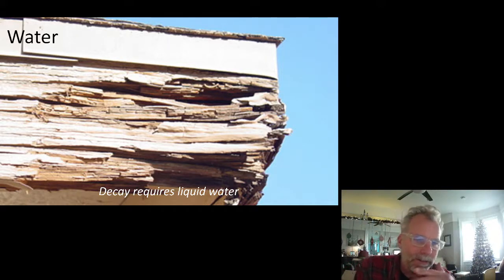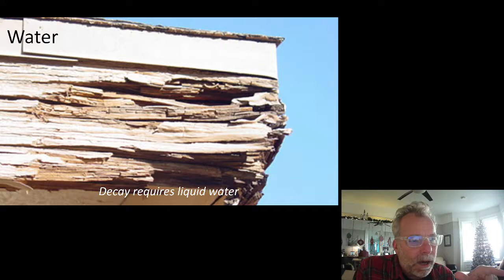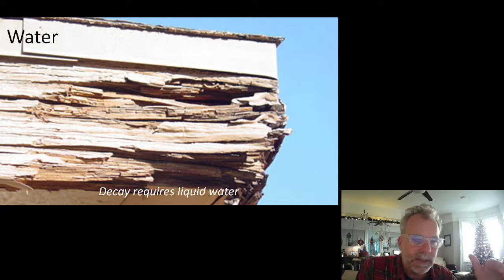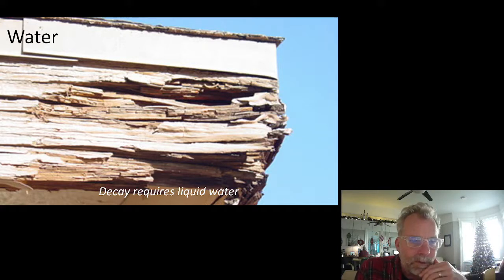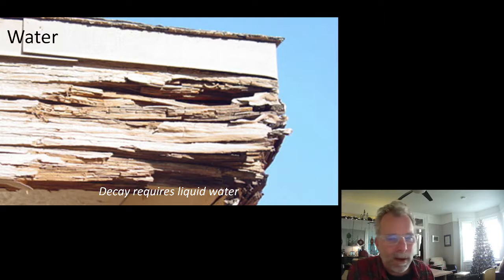Sorry for my snorting and coughing. The one extremely important thing to think about with wood is that wood requires liquid water to decay. In the absence of liquid water, wood will last virtually indefinitely. People talk about dry rot, but dry rot is a misnomer — wood doesn't rot if it's dry. Dry rot is wood that got wet, rotted, and then dried.